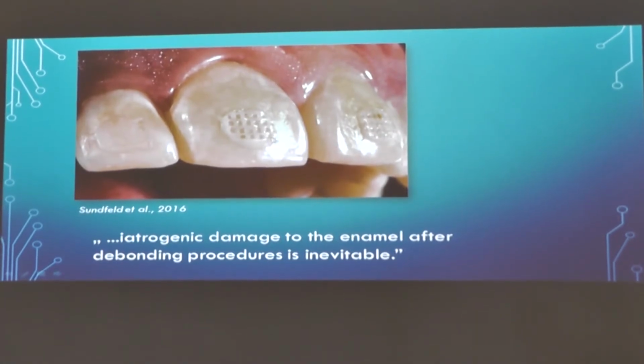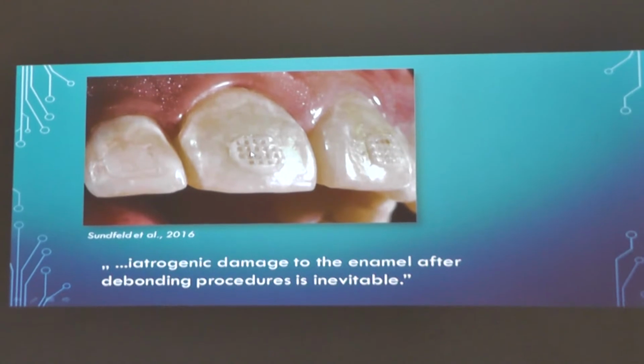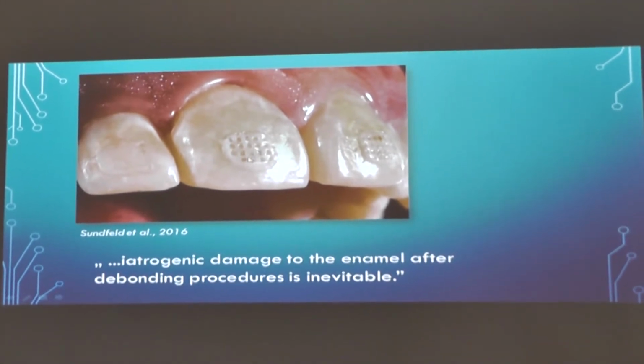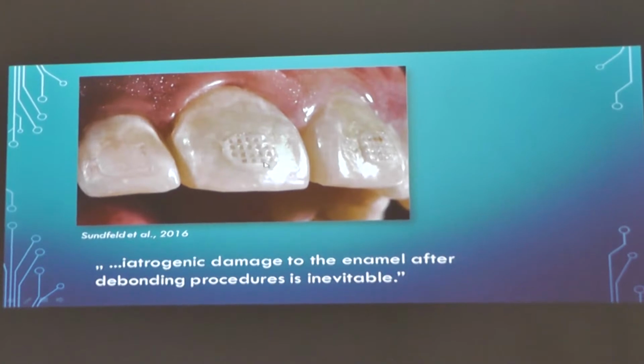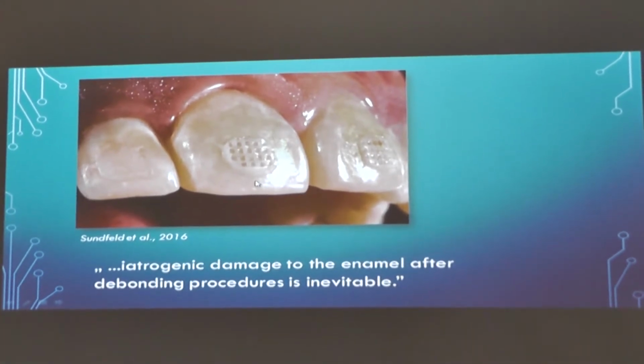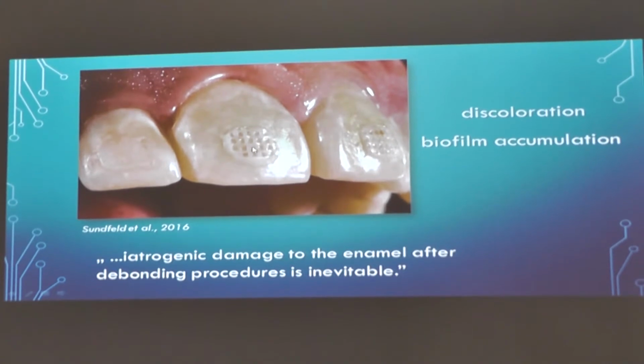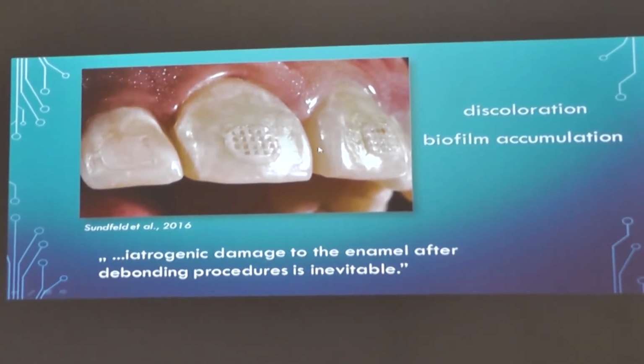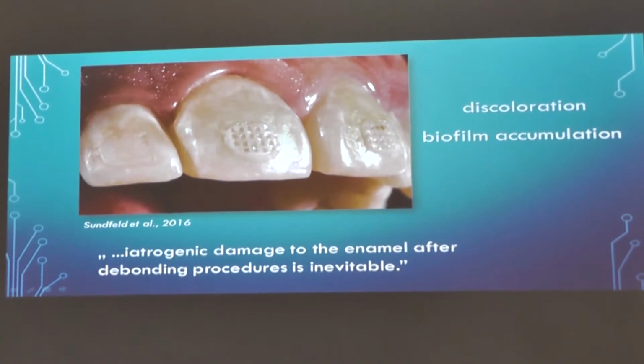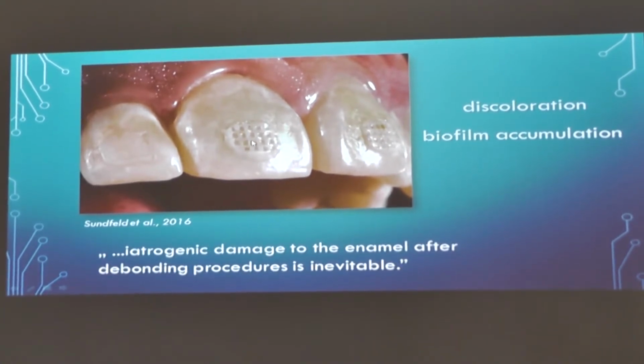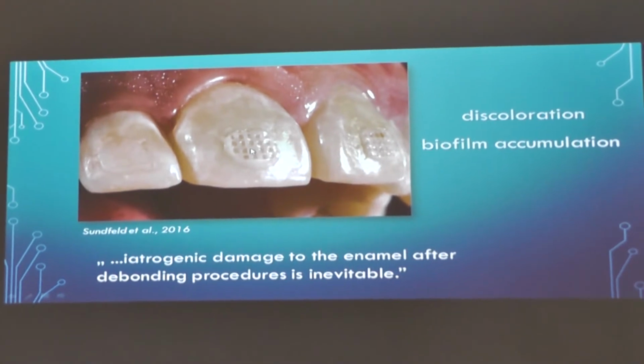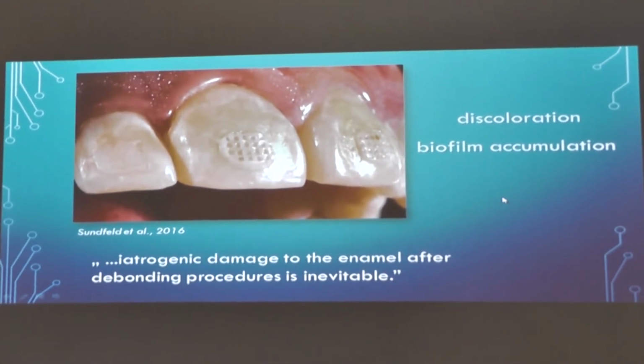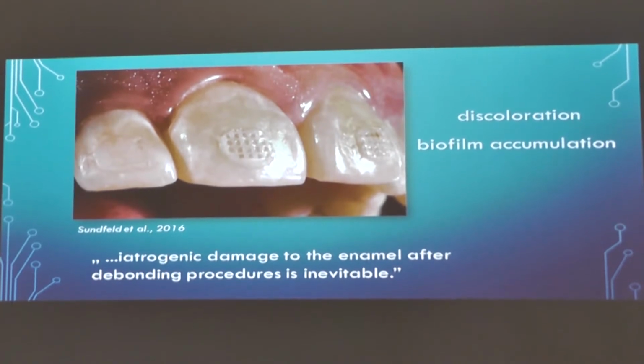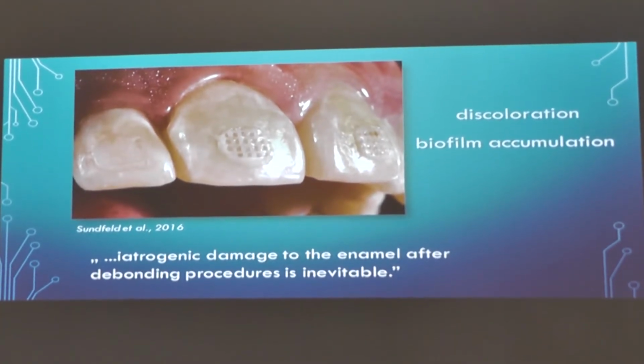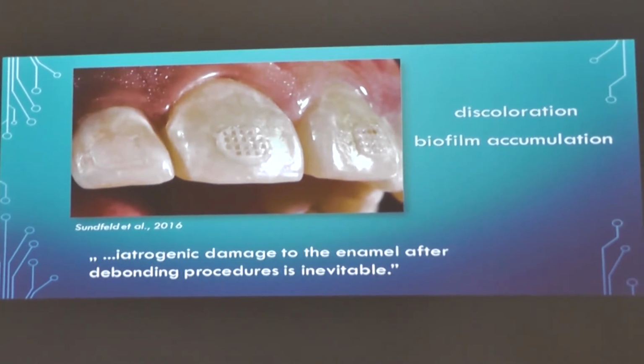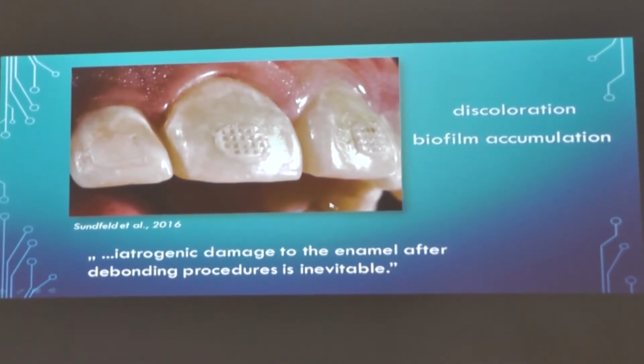And this is an ARI index of 3, so when all the adhesive is left on the tooth. And you can also see this distinct print of the mesh of the bracket base. And this can afterwards result in discoloration and biofilm accumulation. So even if you go and remove the most superficial layer, there will always be some adhesive left in the enamel that is not easy to clean up in a manner sparing towards the enamel. So you will probably, with a burr, remove a surface layer of enamel.